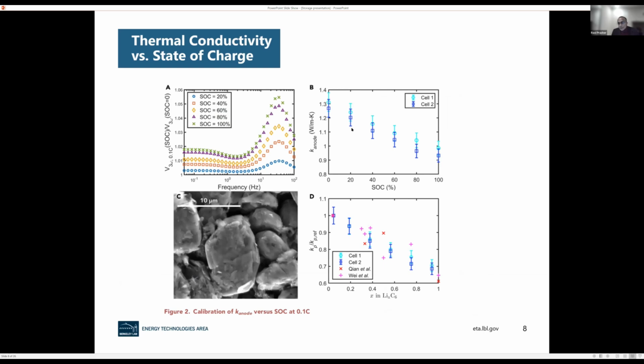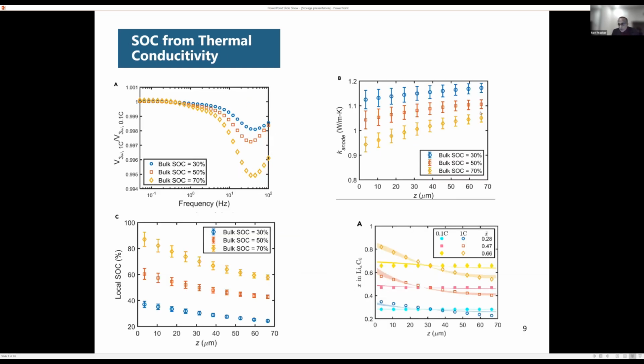and then you can see K anode here. This is what I know from this K anode here, and this K anode as a function of Z, I can map them together and exactly figure out the local state of charge. So even if the average state of charge is 70%, there is a concentration gradient. So the average of this is 70%, but the highest is 90% here, and the lowest is 60% here.